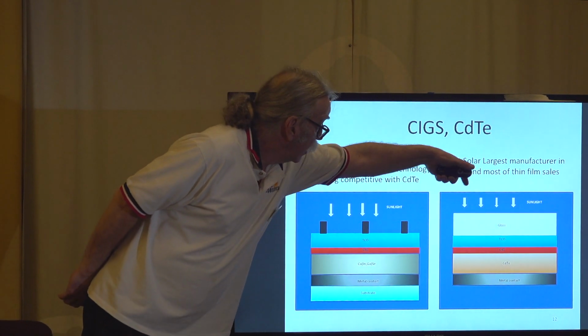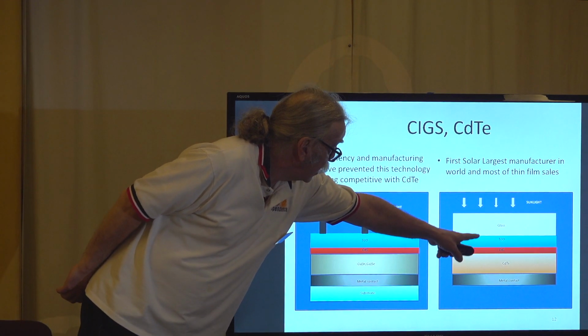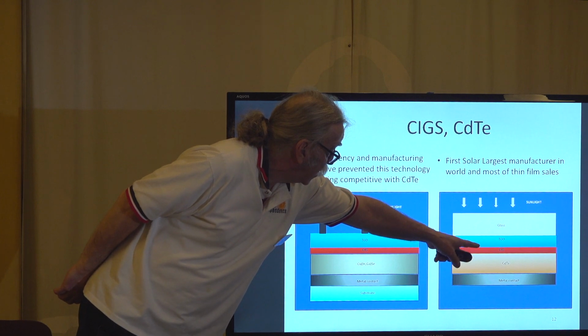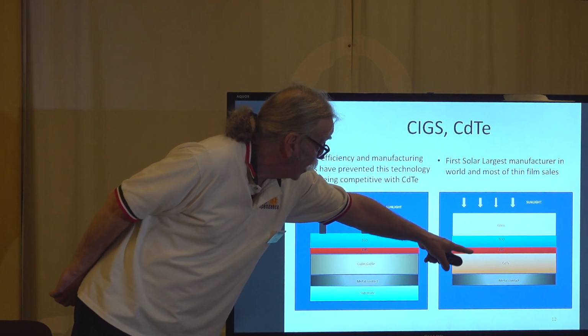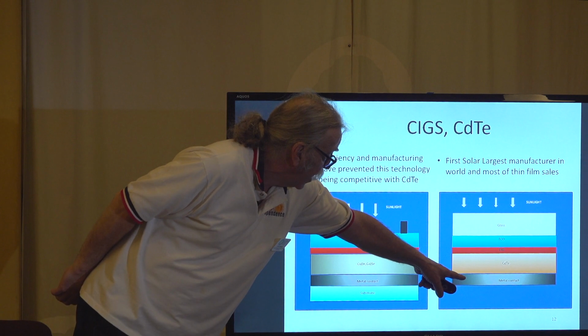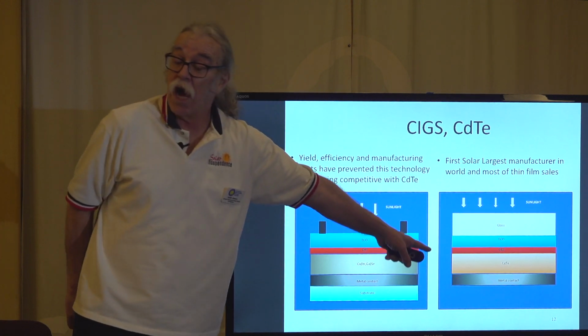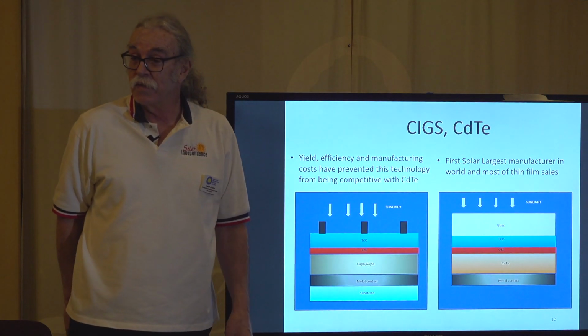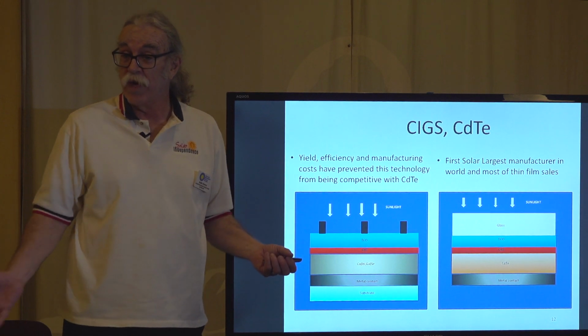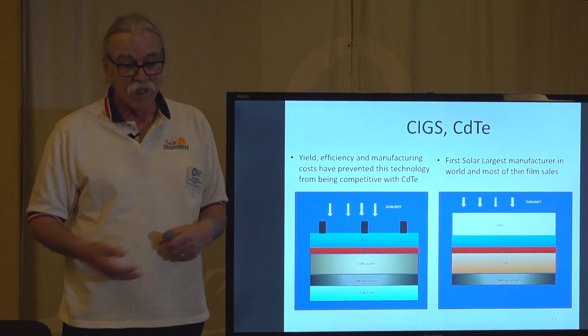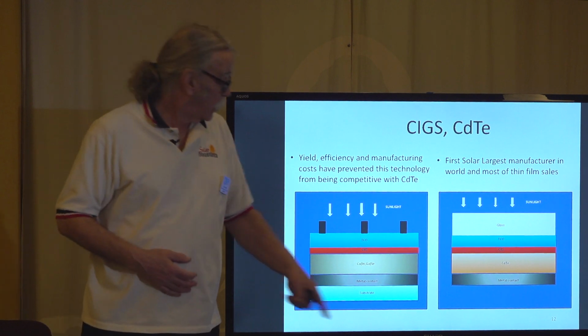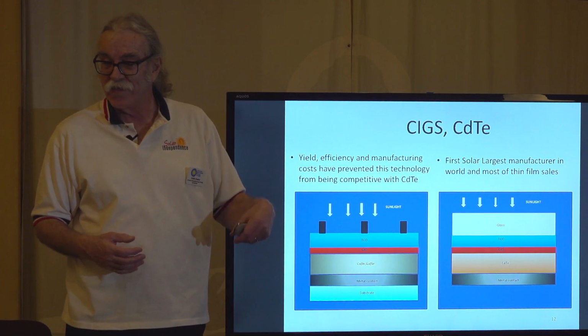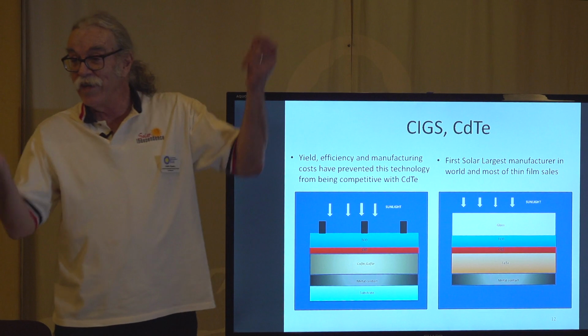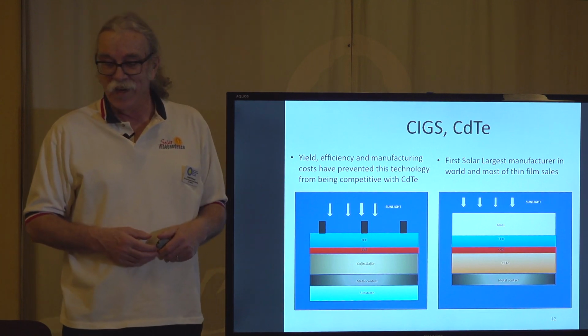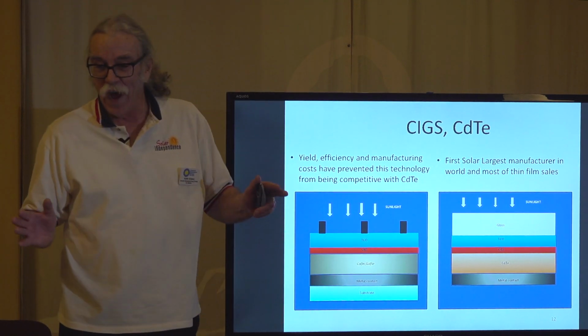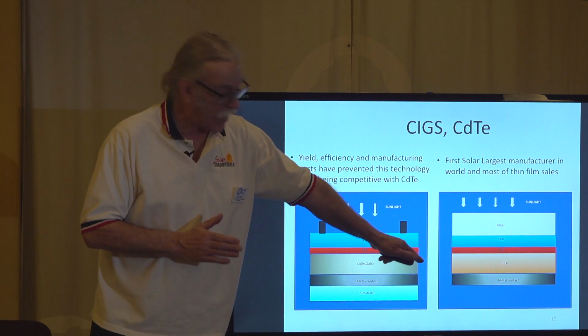Cad telluride, light goes through the glass, it goes through a TCO, which is typically tin oxide, and then cad telluride is the absorbent, then a metal on the back. That metal's a black art for cad telluride. Gold would be the preferred metal, but it goes right through the cad telluride and it's gone after a day. So it's got zero durability. Carbon is what they use now, but it's kind of like a paste, and then they have to add chlorine in there. Chlorine, they don't quite know why, but it doesn't work if you don't add it.